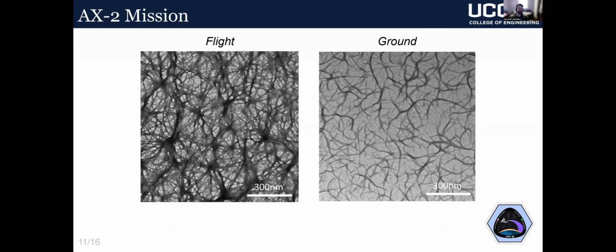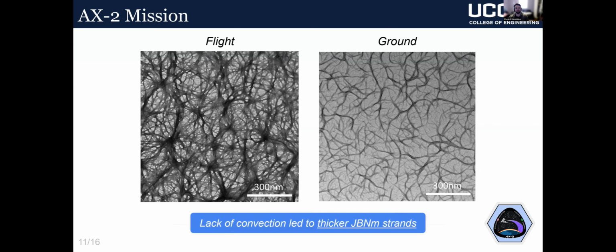To confirm this, we performed transmission electron microscopy, or TEM. This imaging method lets us take high-resolution images of our samples at the nanoscale. These images let us realize that not only were the flight samples more homogeneous, but they also appeared to become thicker in space.